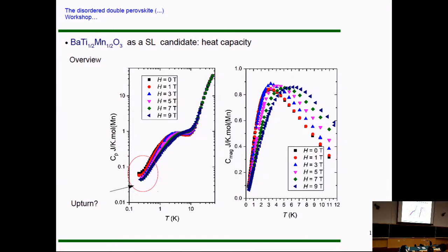other possibilities. And this is the magnetic specific heat capacity that we get after subtraction of the phonon contribution. As you see here, it looks like it goes linearly to zero temperature, but that's not the case. When you fit, you get a different scenario. But I just want to show here this bump, and it turns out that when you increase the field, you displace it to a little bit higher temperature.